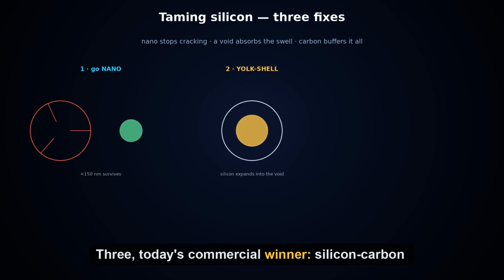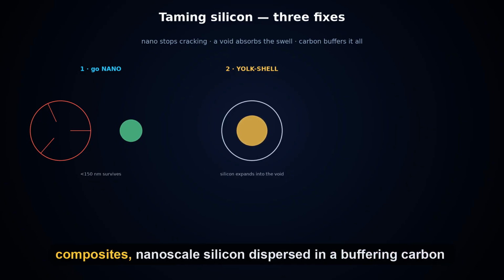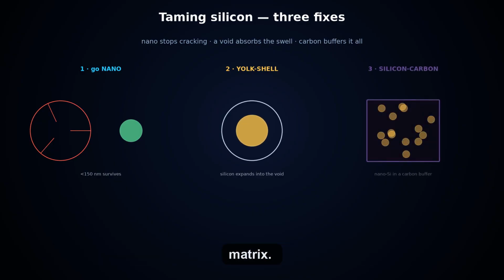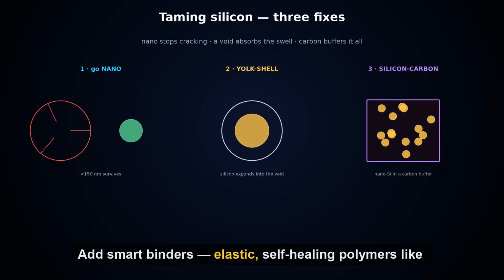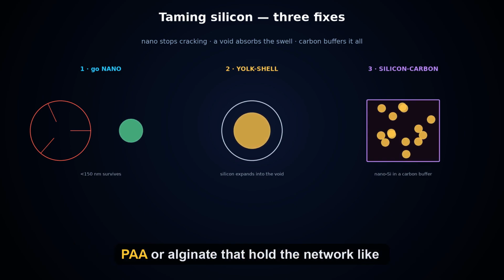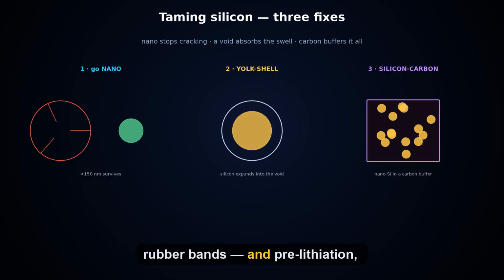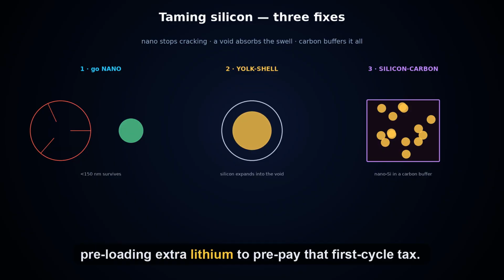3. Today's commercial winner: silicon-carbon composites. Nanoscale silicon dispersed in a buffering carbon matrix. Add smart binders: elastic, self-healing polymers like PAA or alginate that hold the network like rubber bands. And pre-lithiation, preloading extra lithium to prepay that first cycle tax.